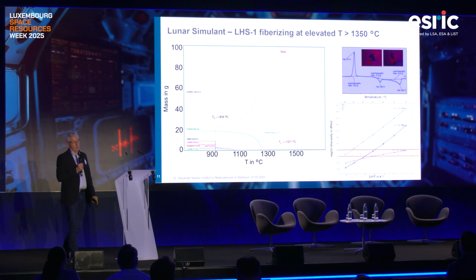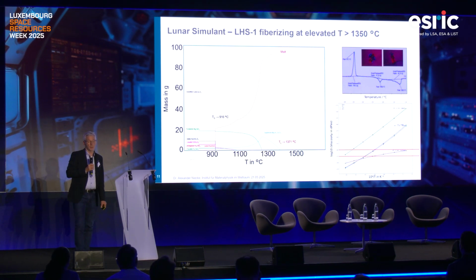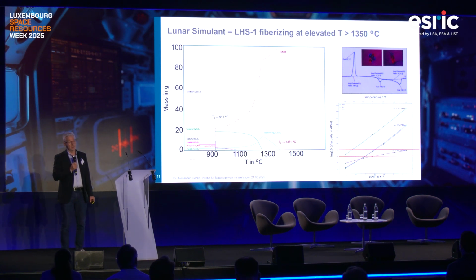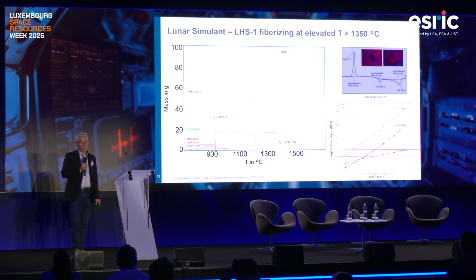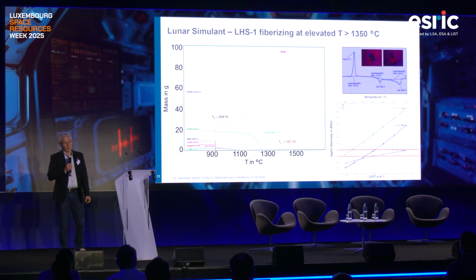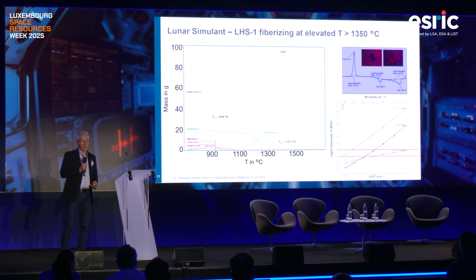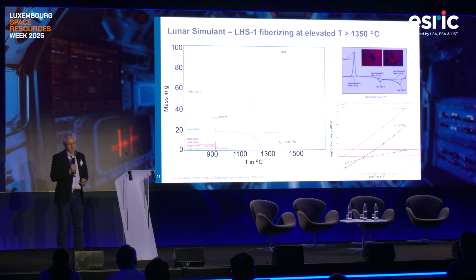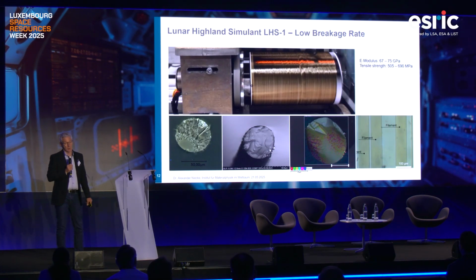The same for the LHS1. For this simulant, a much more elevated temperature was needed because the liquidus temperature and the forming temperature are quite close. But nevertheless, by modifying the setup of our experiment, we were able to produce textile-grade quality endless fibers, also in bigger quantities.